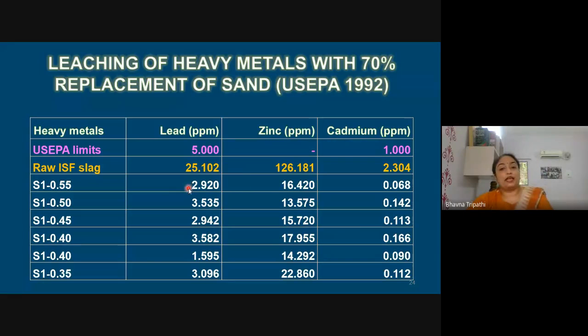However, very interestingly, we got promising results which encouraged us. All of the slag mixes which were tested for TCLP contained 70% ISF slag, and all the limits show a very encouraging result, that the leaching has been drastically reduced. So it gave us a green signal to go ahead for the long-term testing. Long-term testing of all the concrete specimens was conducted for evaluating various parameters related to durability.